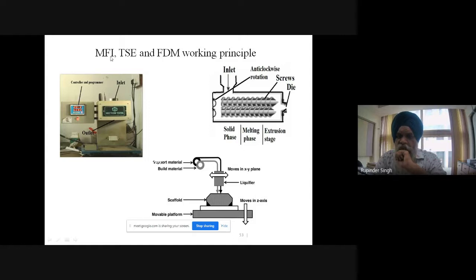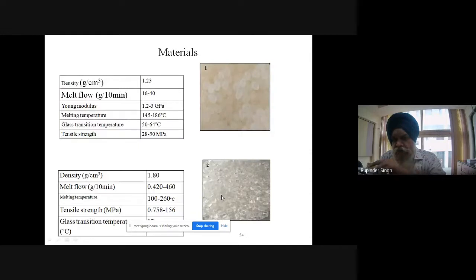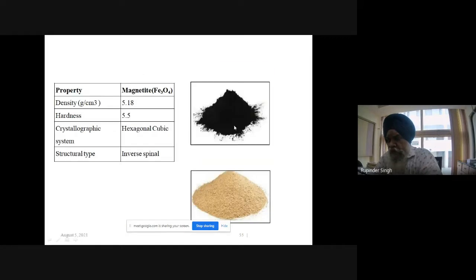So once I control my MFI, then I put my material in the extruder. Once the material is fed over here, there are intermeshing screws, and finally I get a feedstock filament. That feedstock filament or the wire I am putting into my 3D printer, and I am getting a 3D printed part. Now in this particular example, I have selected PLA as one material, PVC as the second material, then magnetite powder as the third material, and this is the wood dust basically as the fourth material. I am interested in reinforcing these four for making a hybrid substrate, right?